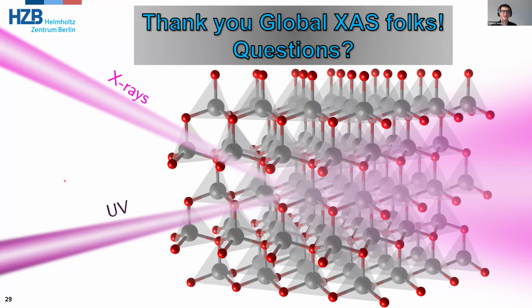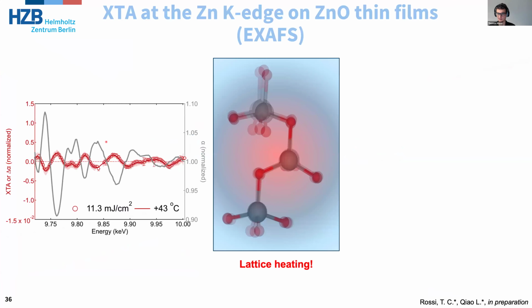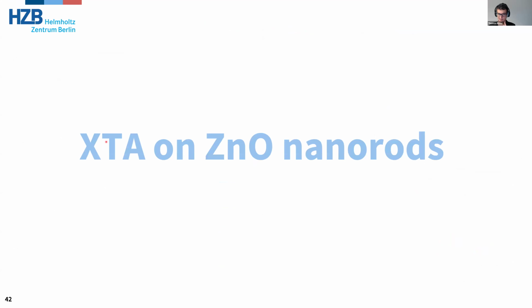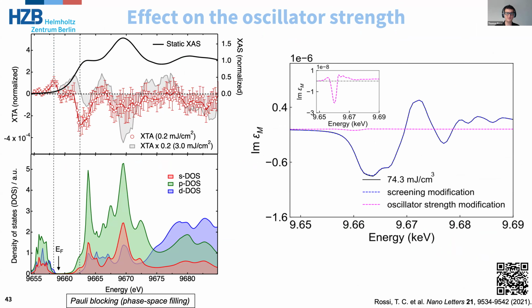And actually, I would like to extend a little bit on that. At the APS, we did a measurement by tuning the pump to below the Mott density. It took us 24 hours to average a signal there, but we still managed to measure it, and we were able to see a signal that differs quite significantly. Actually, I probably have this here. Just one second. It's this one. So the red circles are the 24-hour measurement that's below the Mott density. The gray curve is a measurement that's above the Mott density. You can see that they differ quite a lot, especially in this rising XANES edge.